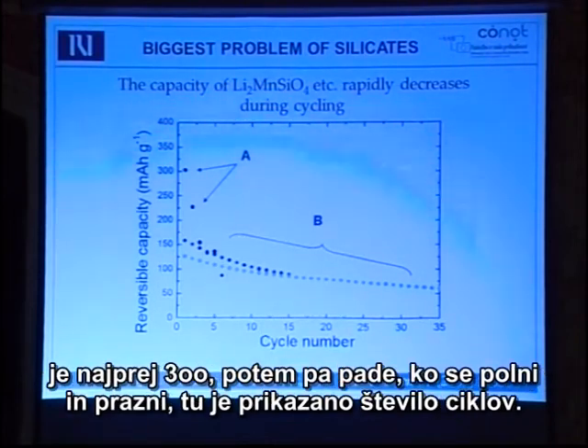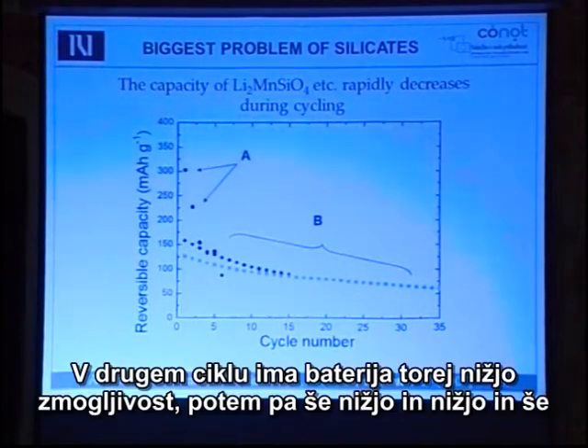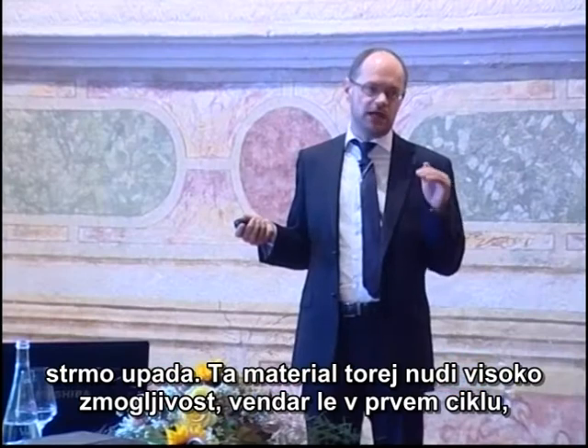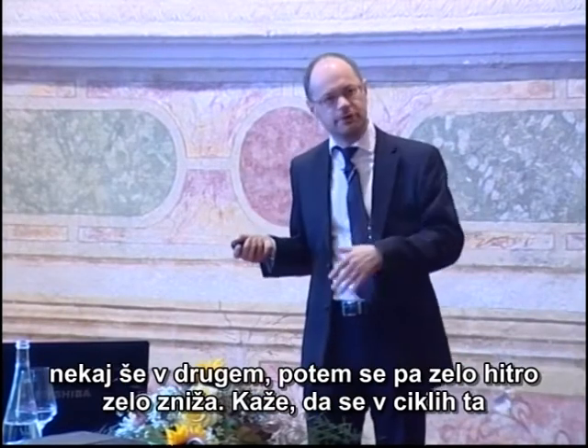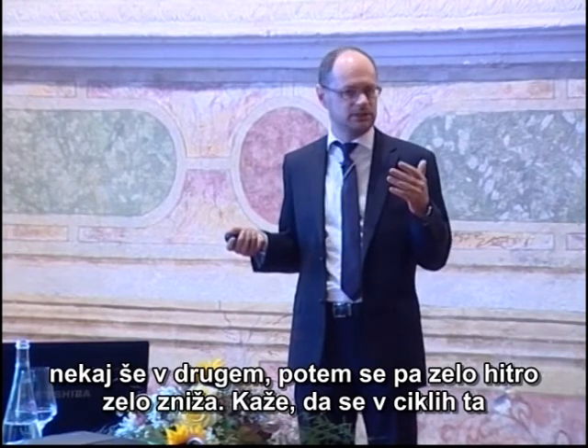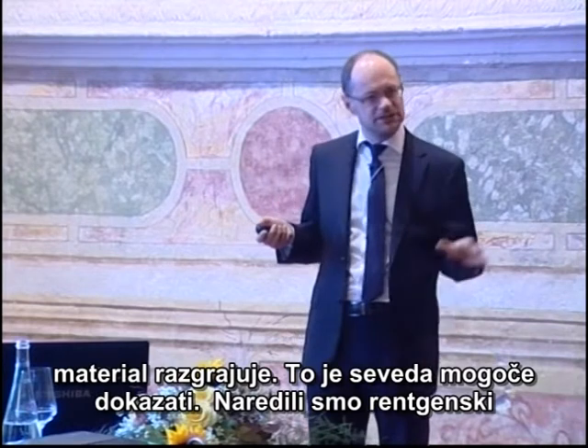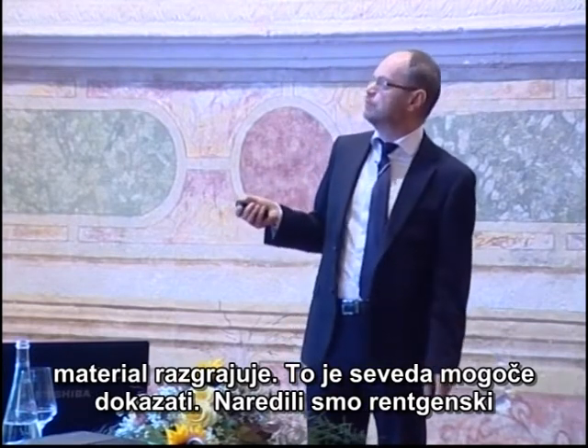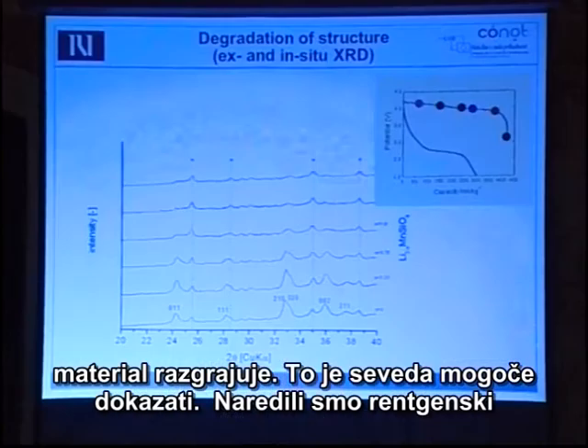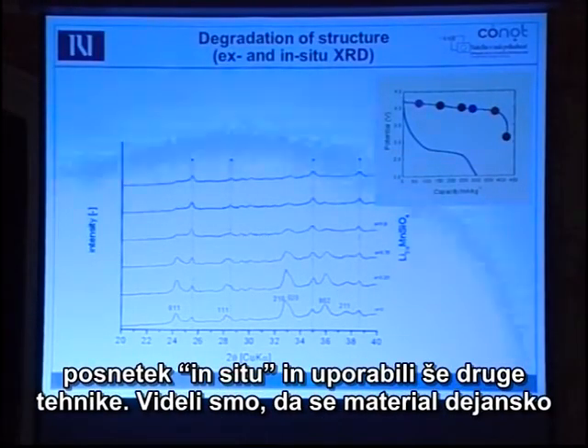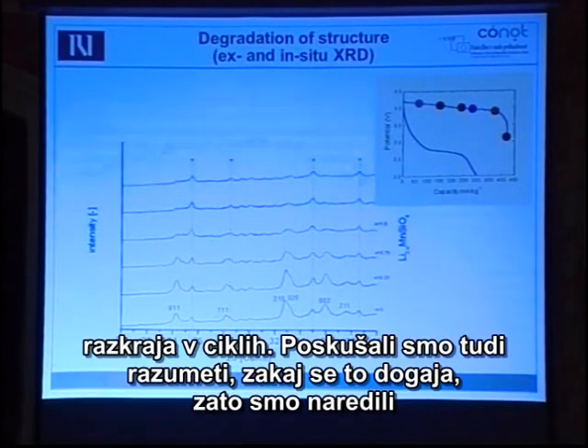The capacity is 300 at first, and then it drops when you charge and discharge. This shows the number of cycles. So the second cycle has lower, the third even lower, lower, lower. It drops very rapidly. So this material gives you high capacity, but only in the first, second cycle, and then it drops very rapidly. So it seems as if this material somehow degrades with cycling. Of course, this can be proven by, for example, in situ X-ray and many other techniques, also EXAFS, and we saw on these graphs that indeed this material is degrading during cycling.